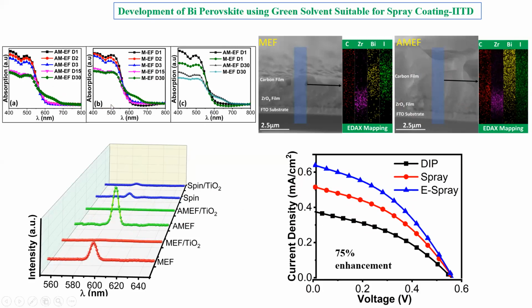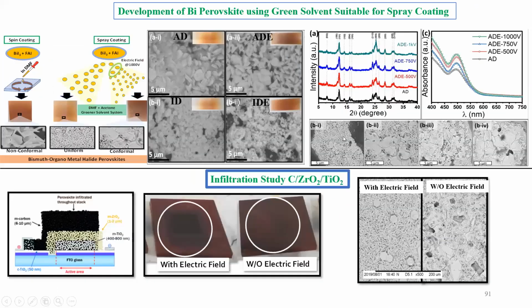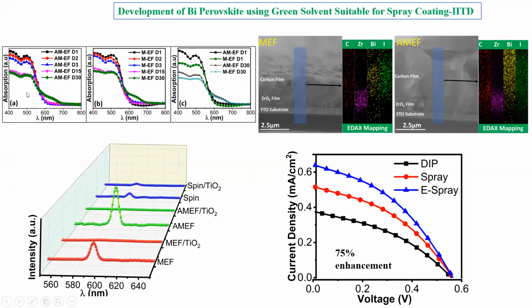And because of that horizontal growth, which I have shown here, and this is porous. If you have a more porous material, moisture goes more inside, and in this film the moisture is repelled because it can't go beneath the layer. We found the stability of the material is very good. When we fabricate something, we study it all the way, and we found that up to 15 to 25 days the material is almost stable. In 30 days, it starts forming some bismuth iodide peak. This is PL, this is UV-visible. We start forming some peak. So overall, this is my research.